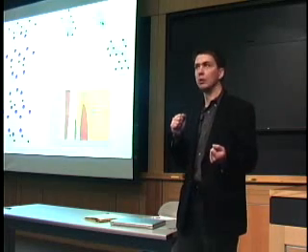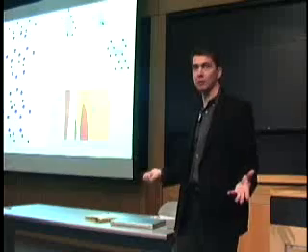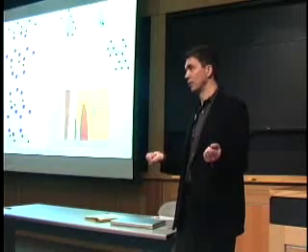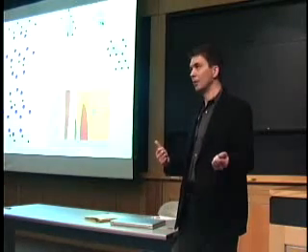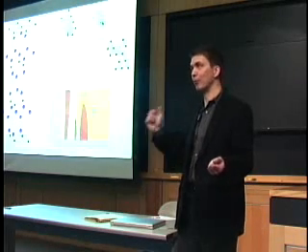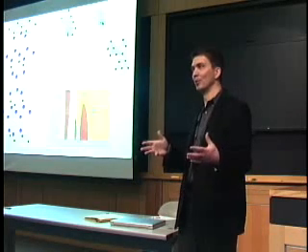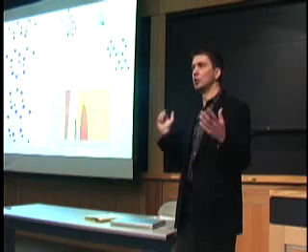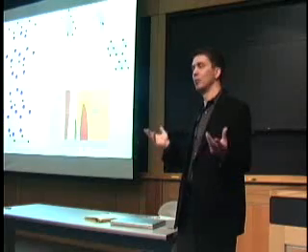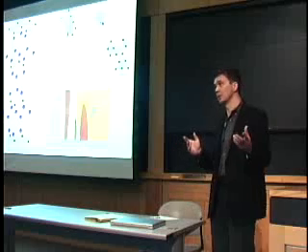And that's why you can make Hamiltonians that are very accurate, but they live on a lattice model, so they're extremely fast to search. I mean, you've done the hydrogen on palladium. That trivial Java code does 4 or 5 million spin flips per second on a stupid old IBM computer. So on a new machine, you can run 10, 15 million spin flips per second. So you can search configuration space extremely fast. Okay? And so that's why it's so good at finding new structures.